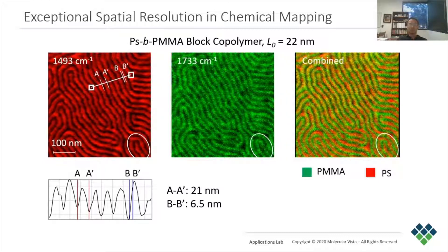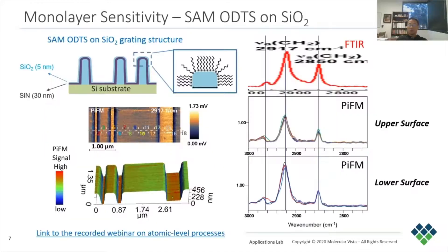We can then combine them to create a chemical map as shown at the far right, where green and red regions represent PMMA and PS molecules respectively. Looking at the area in the white circle, we can see the PS contains a finger-like structure, whereas the PMMA contains the pocket structure for the finger. Looking at the cross-section in the PS image, we can see that the 10% to 90% transition is about 6.5 nanometers, demonstrating PIFM's sub-10 nanometer spatial resolution.